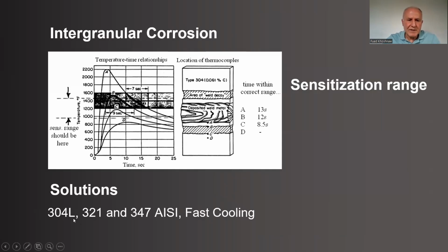So how to solve it? We can use low carbon or other types of austenitic stainless steel that have stabilizing elements. So for example, 321 has titanium, and this one has columbium. These have more affinity to combine with carbon than chromium. So chromium will stay, and these elements will combine with carbon. So this is one protection, or fast cooling, so don't give time for this precipitation to happen.